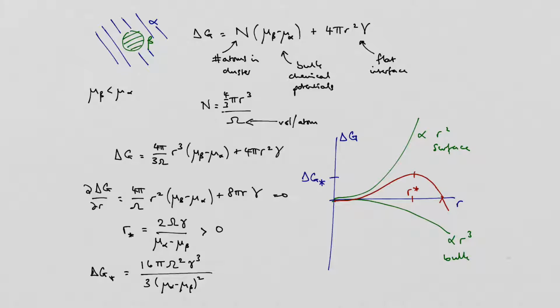So essentially under those circumstances, gamma is naught. It's not that as things evolve and finite changes occur, you won't end up with interface. You very clearly do when you look at the micrographs of things that have gone through spinodal decomposition, and you see very clearly the stripes and the interfaces between them. So there are interfaces there, and they will cost energy.